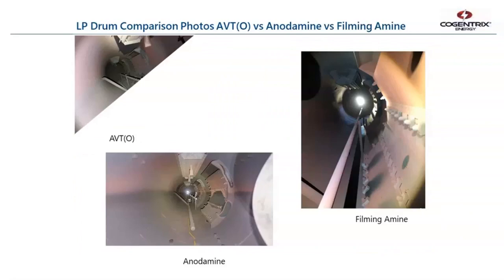Here are some drum photos. This was the 3 different programs practiced at the same time. It seemed to do a little bit better in the drums. You can see the anodamine. The spots around the belly pans have that weird effect where it boils. The metal appears to be passivated, where there's the shiny spot by the belly pans, but it didn't peel back over with hematite.